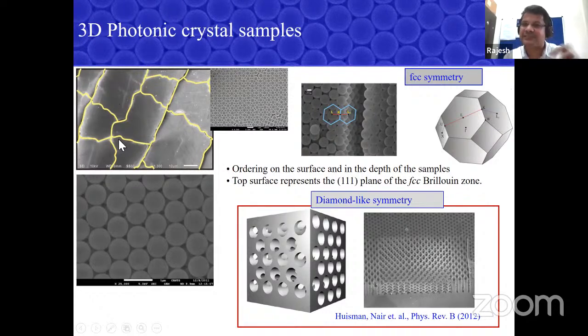It looks like a cricket pitch because during the sample growth, it got all these cracks and it became like pieces. And this is an image of the sample. If you take some small region here, it looks very nicely ordered. Usually people show these kinds of pictures, and you think that everywhere the sample looks like this. That's not true. You have a lot of defects, a lot of cracks, a lot of bad things also happen. So this is a kind of crack. You can see that on both sides of the crack also, it is nicely ordered.